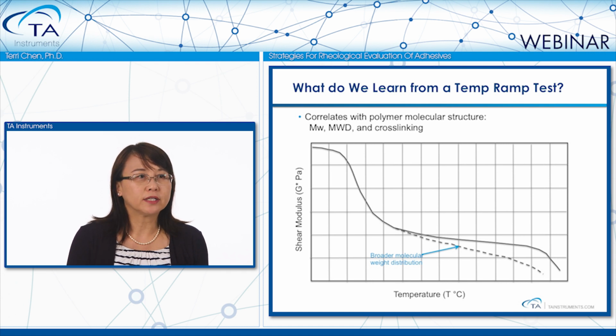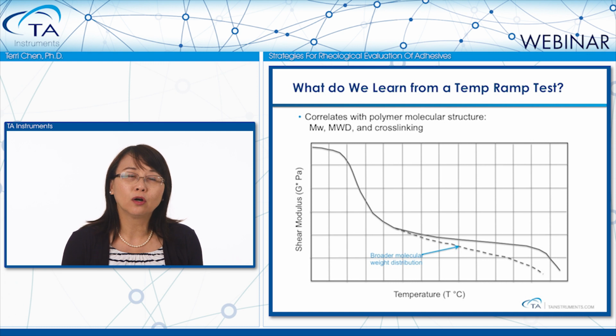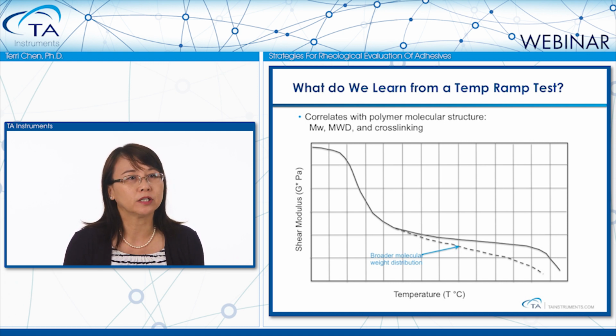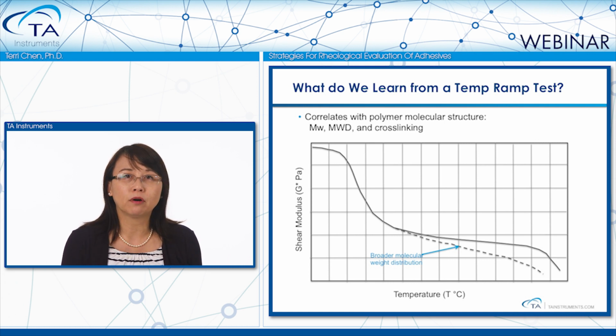If after the glass transition, the polymer shows a continuous decrease in G' or G" instead of having a relatively flat rubbery plateau region, then it indicates that this polymer may have a broader molecular weight distribution.